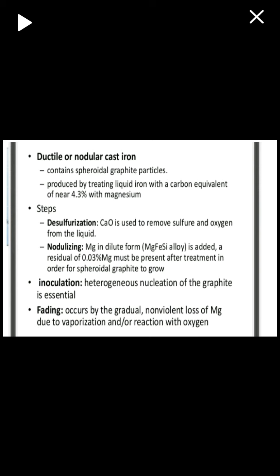Magnesium is diluted from MgFeSi alloy, magnesium ferrous silicon alloy, is added. A residual of 0.03% magnesium must be present after treatment in order for spheroidal graphite to grow. Then inoculation. Heterogeneous nucleation of the graphite is essential. Fading. Fading occurs by the gradual, non-violent loss of magnesium due to vaporization and reaction with oxygen.